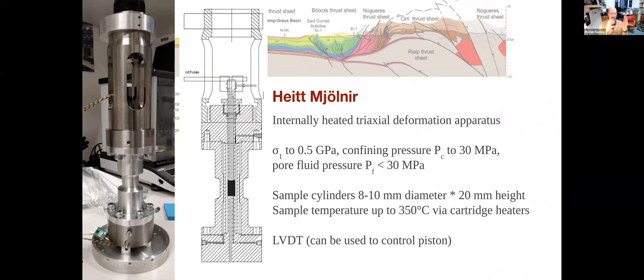And at those temperatures, we can get away with a relatively thin aluminium alloy pressure vessel. It's a 7000 series, pretty fancy alloy. But that is thin enough so that we can comfortably see through. But the strength of that aluminium drops off at 150 degrees Celsius. So we always have to keep below that. And the temperature management in here happens through a really complex set of heat guides and thermal baffling. And that took us pretty much the entire pandemic to develop.